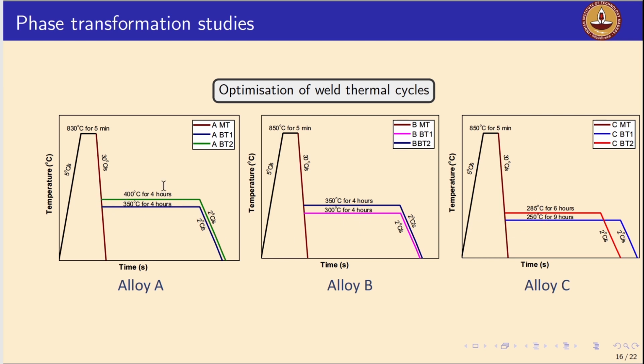So we carry out extensive experiments at various temperatures. I'm just showing you two such isothermal bainitic holding conditions, to give an idea of how changes in these holding temperatures can change the microstructure, and how we can optimize it. We can now understand the exercise of optimizing the interpass temperatures and the post-weld isothermal bainitic holding temperatures by looking at these three conditions. To make the presentation clear, we assume three conditions: for alloy A, the complete martensite transformation, bainitic holding 1, and bainitic holding 2, and similarly for alloy B and alloy C.